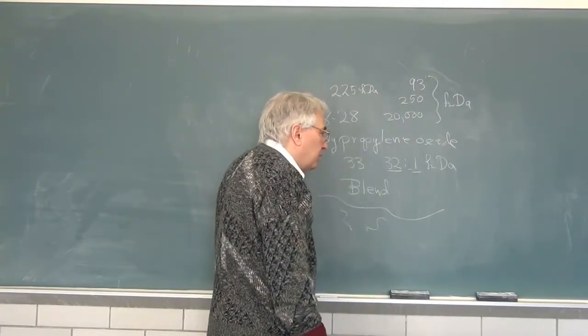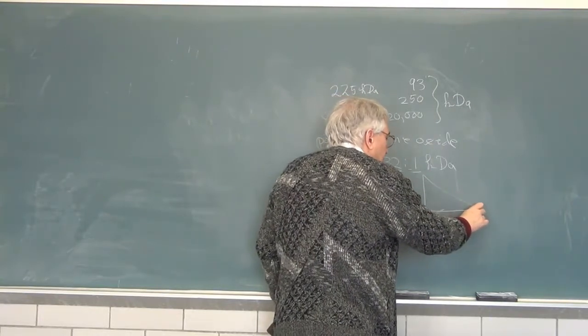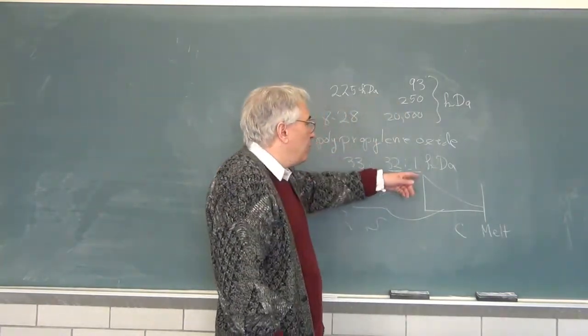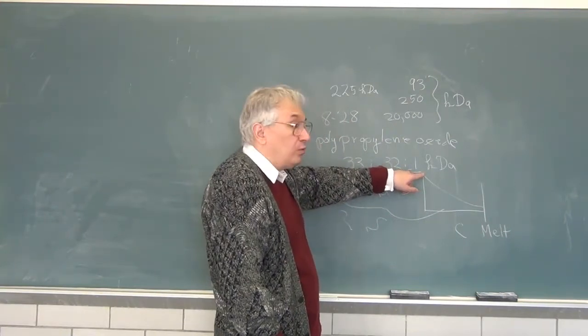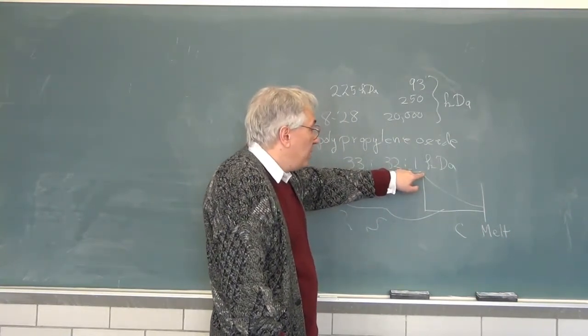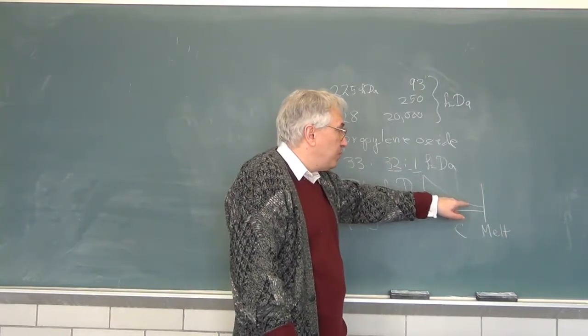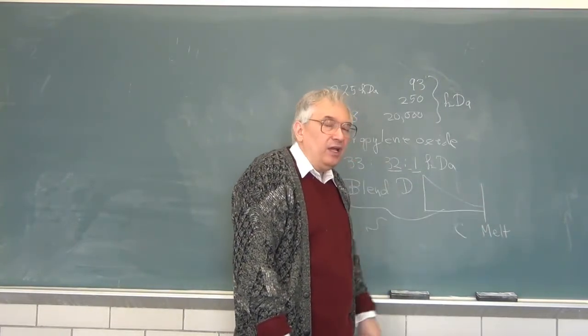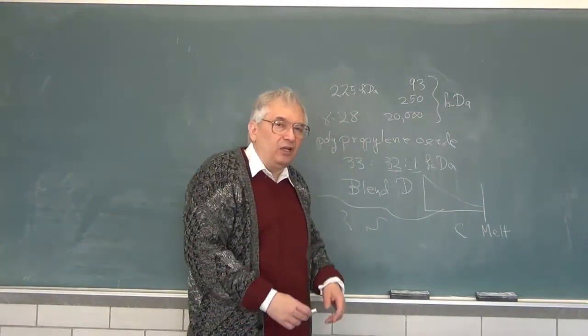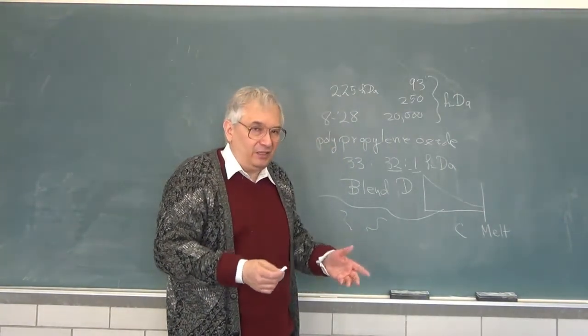However, because your solvent is simply the low molecular weight version of the same polymer, you can do the measurements of D versus concentration on some scale, and you can actually, as it was done, take the measurements out to the melt. That is, you start out with dilute matrix polymer or no matrix polymer, just the probe. You add matrix polymer, and you end up out here, and eventually there's nothing but matrix polymer, no solvent at all. That's what a melt is.